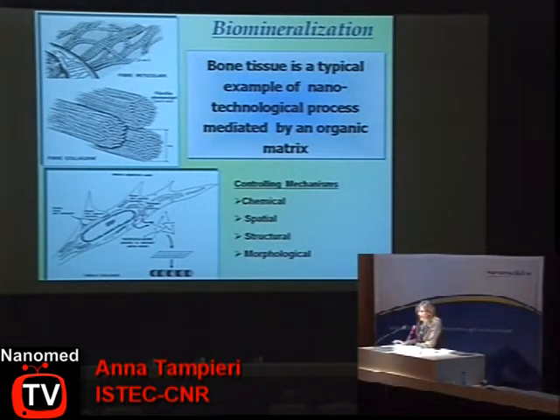Biomineralization is a typical example of a nanotechnological process that nature uses to build bone tissue. During this process, the mineral phase is structurally confined by the organic template, which is collagen, which in turn acts by transferring at the molecular level a lot of information to the mineral phase. Actually, during this process, a lot of controlling mechanisms are active, which are able to affect the chemistry, the microstructure, and the morphology of the final biohybrid composite.